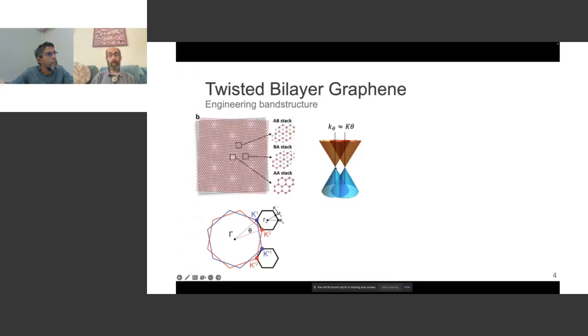And you can see that if you have two cones, one for each layer, that are starting at different points in momentum space, then the two cones are going to cross each other. And one thing that we know that's very basic in quantum mechanics is that unless there's a symmetry reason forbidding it, when two states have the same energy, a reorganization occurs so that they hybridize with each other, and you have one energy below and one energy above. And indeed, that should happen in this case. So you should get a splitting. Instead of having two overlapping cones, where the two cones overlap, you form a gap, a region of energy where there are no states available.